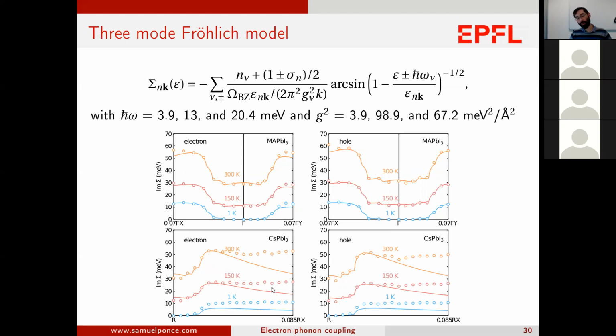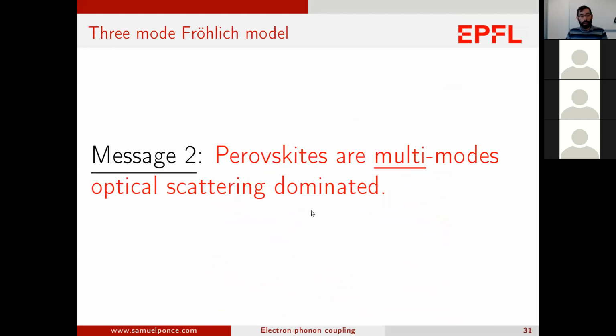And of course, if you go to higher energy, you can see that the agreement is less good. This is simply because we go outside of this parabolicity regime. But for all the states relatively close to the band edge, this is extremely good, and this is what we need for the mobility. And so the second message is that perovskites are multi-mode optical scattering dominated.